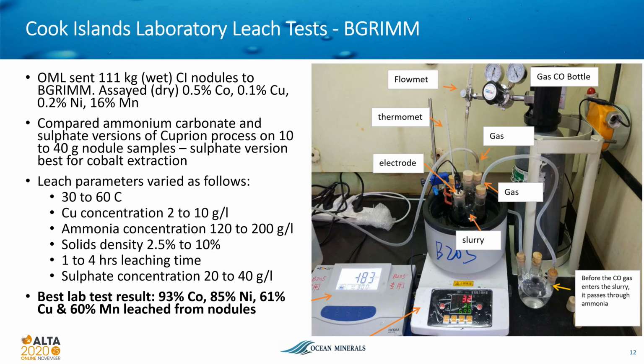While the extractions of nickel and copper were somewhat less, this reflects the lower feed grades, and possibly those extractions being better at slightly higher temperatures. However, the main value is in cobalt extraction. A limited amount of testing has been done on manganese, and the initial leaching tests indicated about 60% was solubilized.